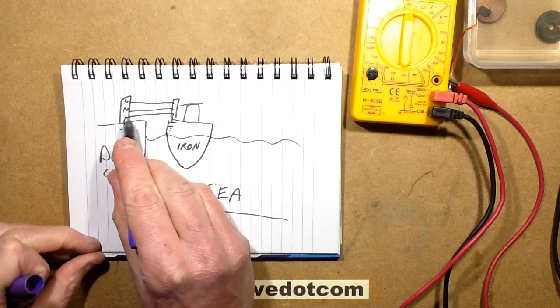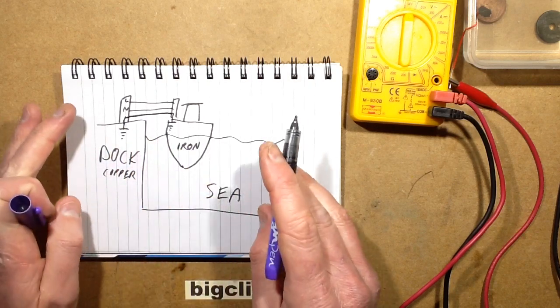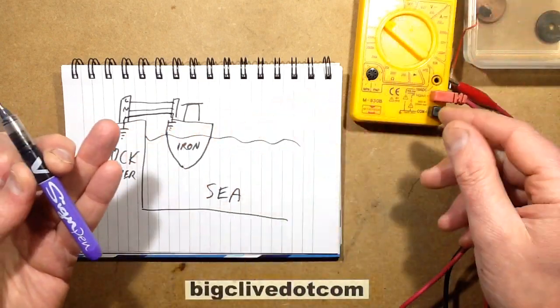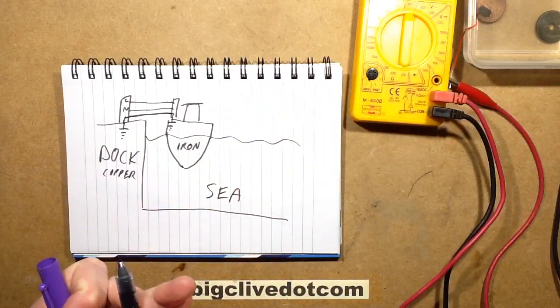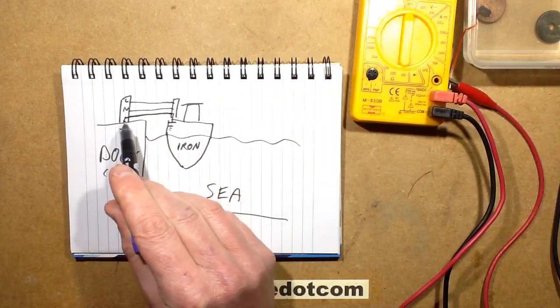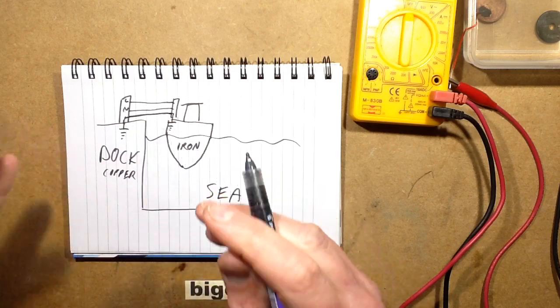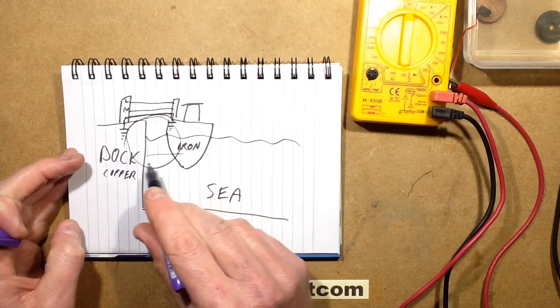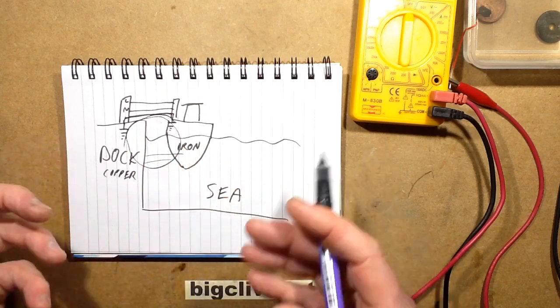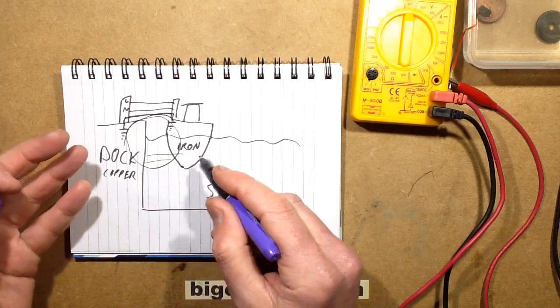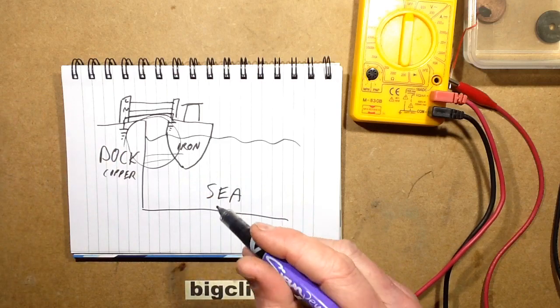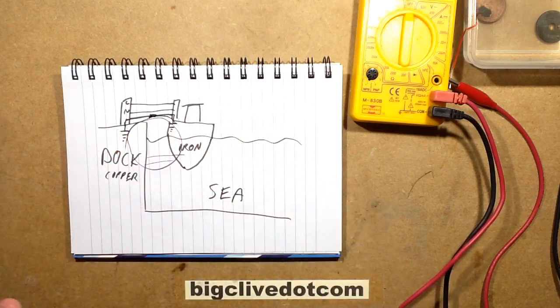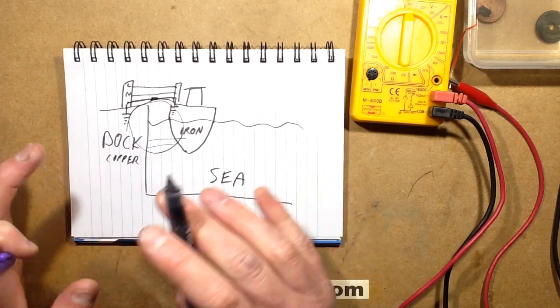Here is what actually happens. You see this earth connection here. Keep in mind you get the two bits of metal, but in this case it's really low, it's a fraction of a volt differential, but it's enough to cause current flow along that earth wire, that earth bond, and cause that current path through the salty water and through that wire that causes the rapid corrosion and the destruction of the iron. So what they do is they break the earth connection and they don't just break it clean. You can't do that for safety reasons. You can't break the earth connection. It just needs to be there for safety.